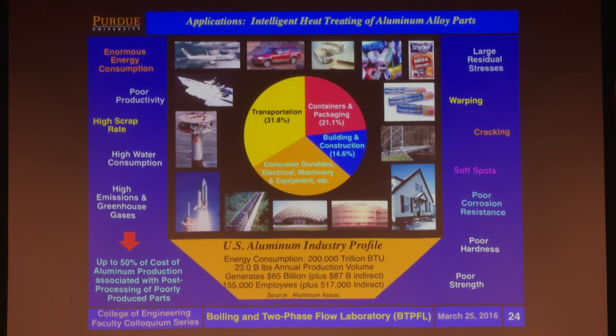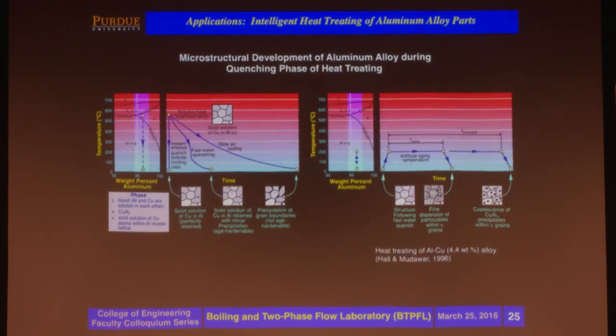Now, one important application I always like to highlight is materials processing. How boiling is also important in materials processing. I'm using aluminum as an example, but you can apply it for steel, for any other alloy. The idea here is summarized in this plot, where you take your metal alloy sample, preheat it to a temperature close to the melting point, and then what you want to do is quickly quench it down to room temperature, but ideally freeze the microstructure that you had before so that you can reheat it in subsequent processes in order to produce this behavior. You have hardening solutes dispersed evenly throughout the crystals.